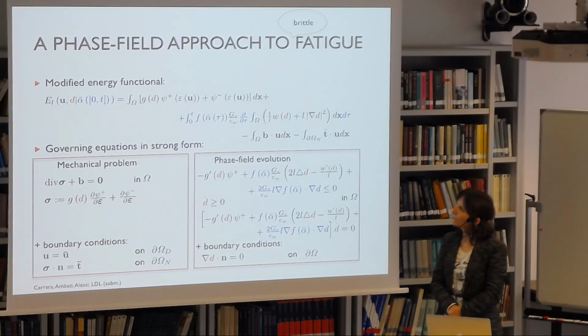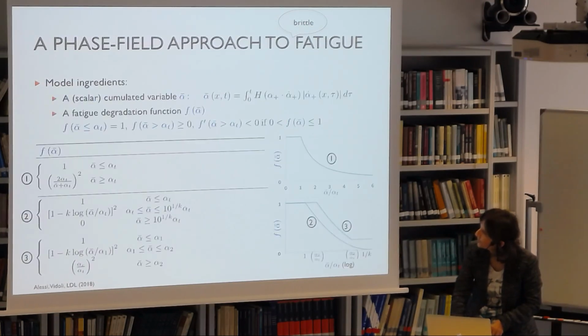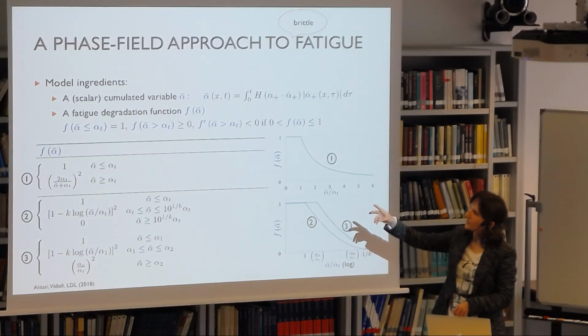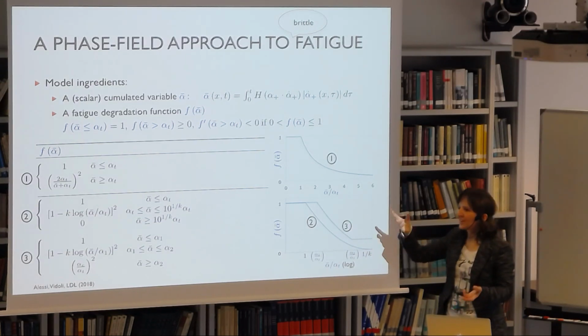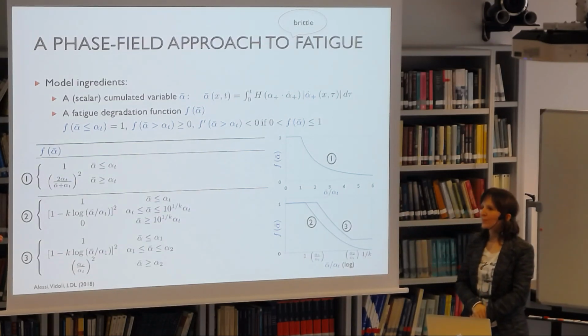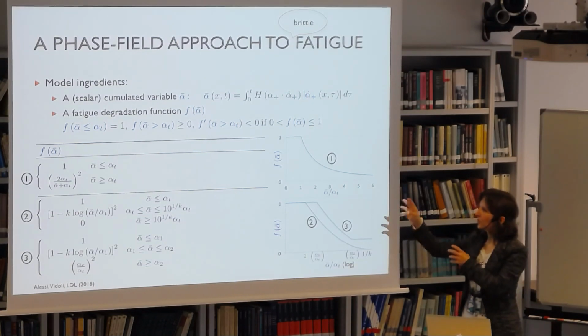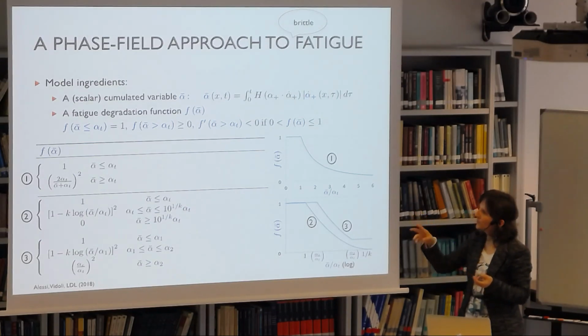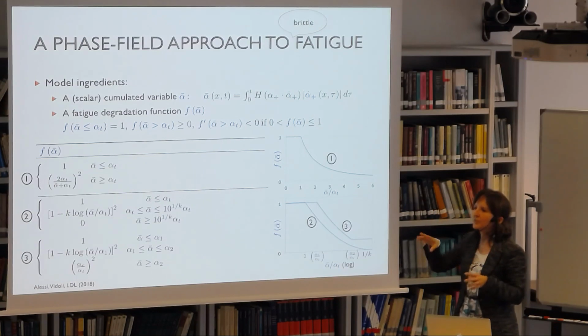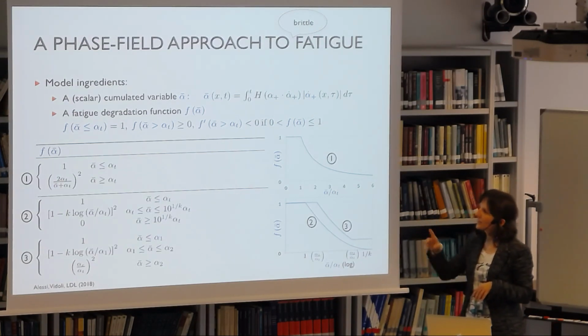Can you justify this thermodynamically? What seems quite strange to me is that imagine you have a very small loading, so you do not have damage at all, and you cycle, you will decrease the toughness in this way. There is a threshold, so in this fatigue degradation function there is this alpha t, a threshold below which nothing happens. So the function is related to the threshold that you have for damage? Yes, we always connect this to the threshold in the damage. Some computations were done with the quadratic model, in which case you have damage immediately. But afterwards, we switched completely to the linear model, and in that case, we connect the two. So if no damage occurs, there will also be no fatigue degradation.